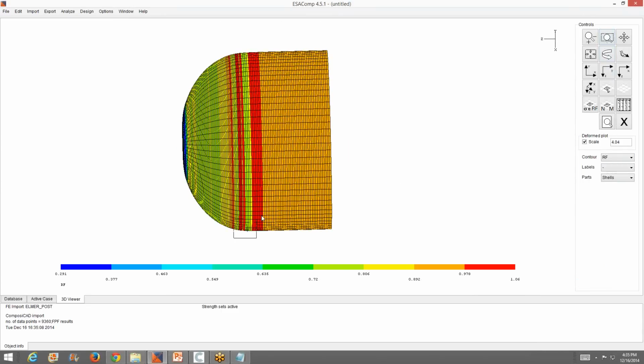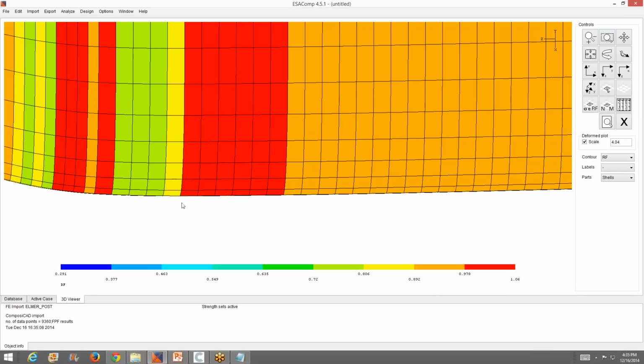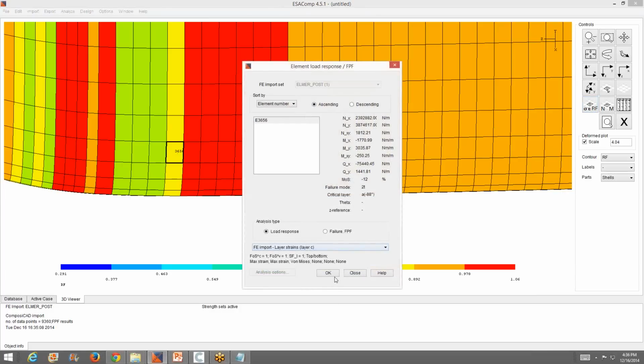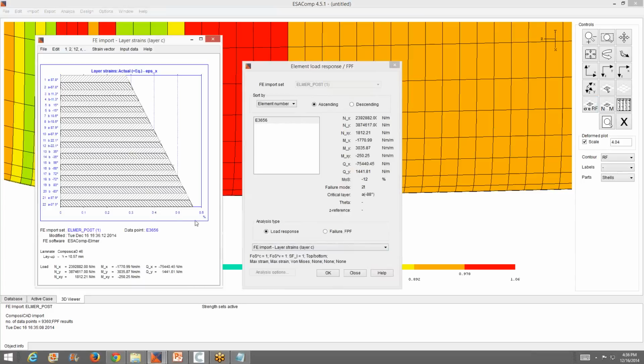So now the mesh is different. Still there's some oscillation of the reserve factor at this region, and I'm going to make a point-wise analysis at this region. By far, the failure analysis has been made only using in-plane failure criteria, but by experience, you may know that the typical region where the tank fails is this one. So let's take a look at this region more closely with the local analysis. And the strains, there's nothing exceptional. They are pretty close to the fatigue limit that I have used.